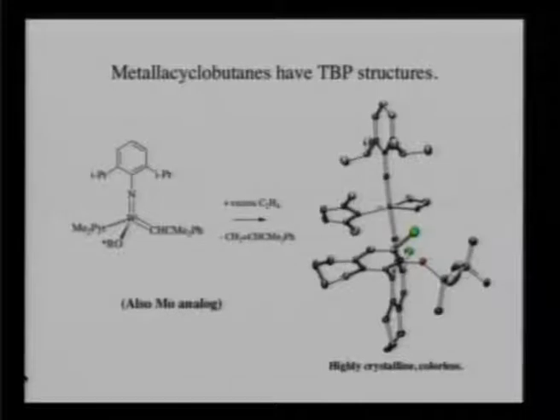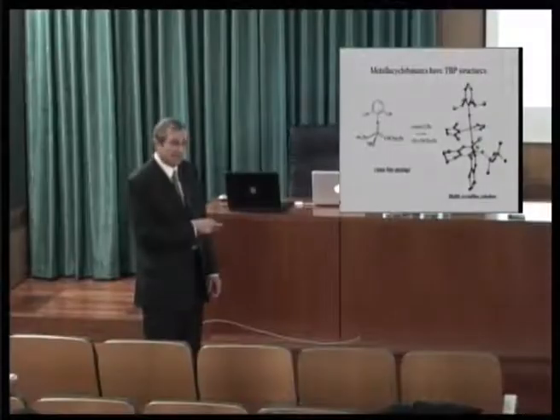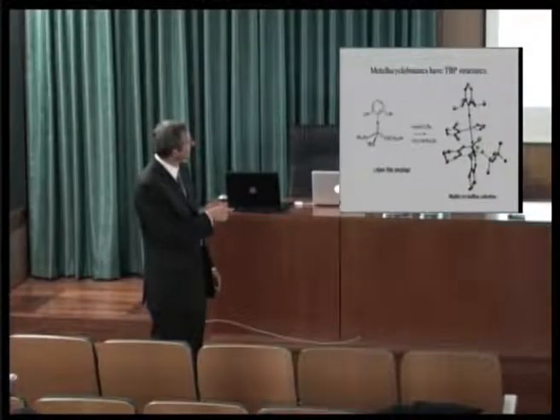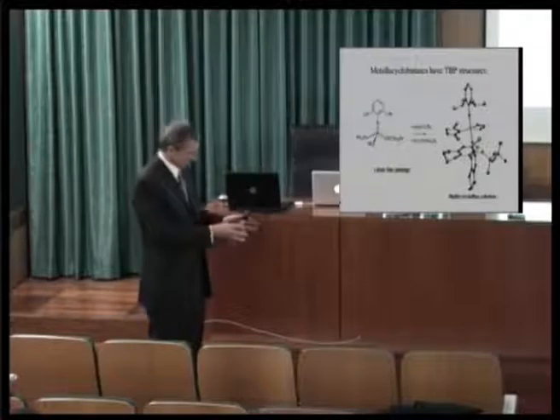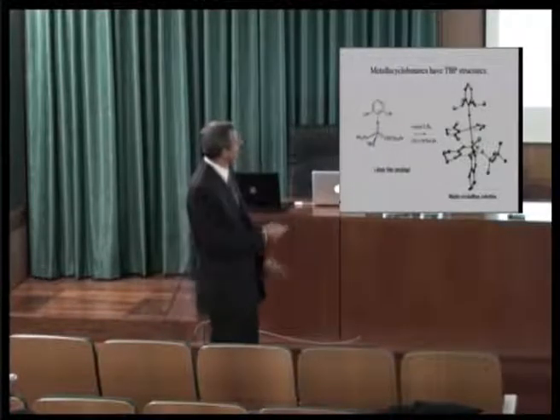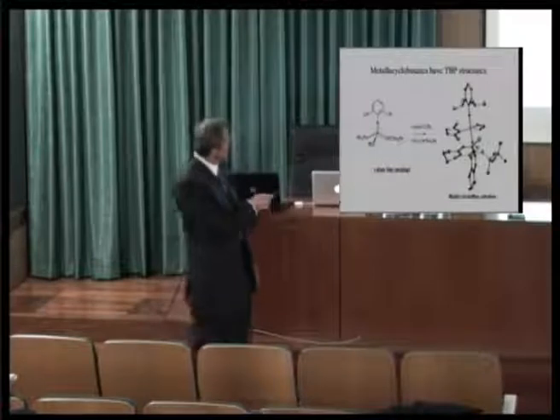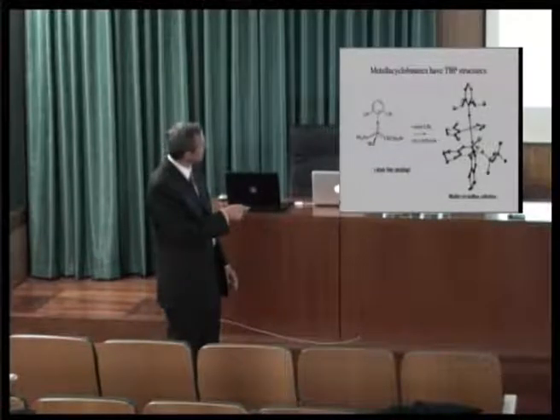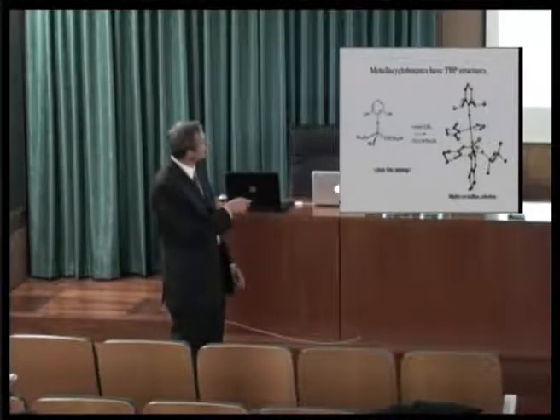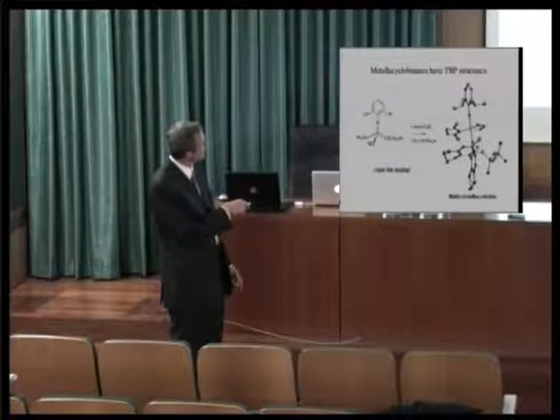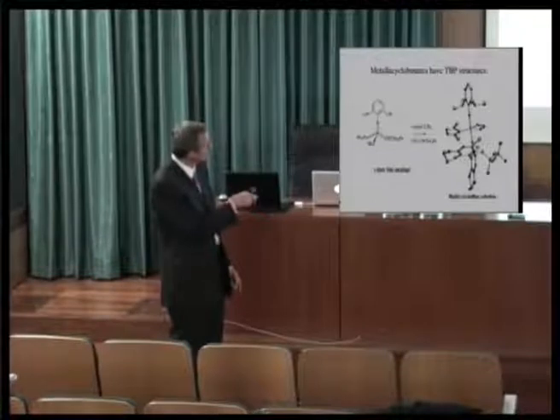So if you take one of these MAP catalysts, this happens to be one of the diastereomeric versions, and add ethylene, you do make a metallocyclobutane, unsubstituted metallocyclobutane, which is the most stable of the metallocycles towards loss of olefin. And it has this shape, a trigonal bipyramid. This is this big chiral ligand that I mentioned at the bottom, and the diisopropylphenylamido group at the top. There's the metallocycle and the dimethylpyrrolide in the equatorial plane of this trigonal bipyramid.